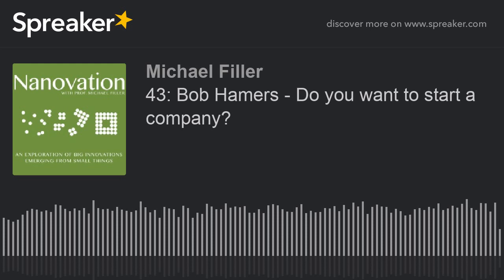What actually mattered was the surface area. If we simply measured the total surface area of the material, we could actually predict what was going to be the impact, both in terms of how much of the metals were released, but also what was the biological impact of the material. This is important because in the field of nanomaterials, a lot of people feel that we don't have any predictive capability. There are many variables, and if you have to test every single combination, it becomes completely burdensome to develop any kind of predictive ability. So this was one small example where we showed that we actually could develop a predictive ability if we simply knew one parameter, the surface area of the material, that dictated the properties.